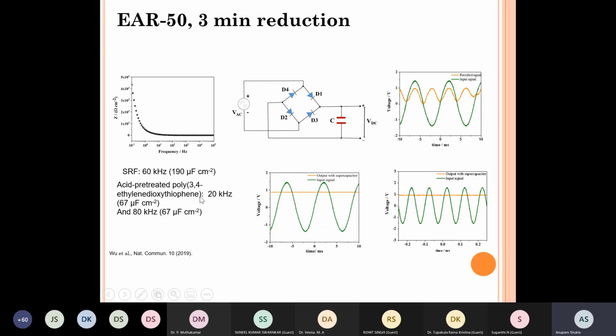So for example, the best values which are reported are at 20 kilohertz, a capacitance of 67 microfarads per centimeter square, or at 80 kilohertz, a capacitance of 67 microfarads per centimeter square. These are all carbon-based electrodes, acid treated poly(3,4-ethylenedioxythiophene). So these are all polymers which are then partially reduced to carbon. For our capacitor, there is something called SRF, which is the maximum frequency at which the capacitive behavior is shown. After that, the inductive behavior comes in. So that's a minimum in the curve. Of course, it is not shown here, it does not become that visible.